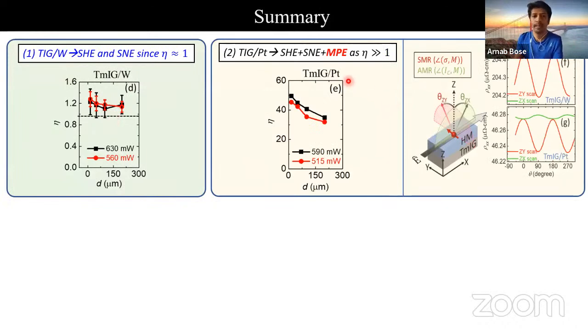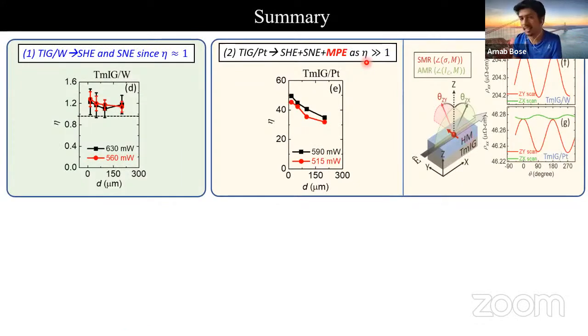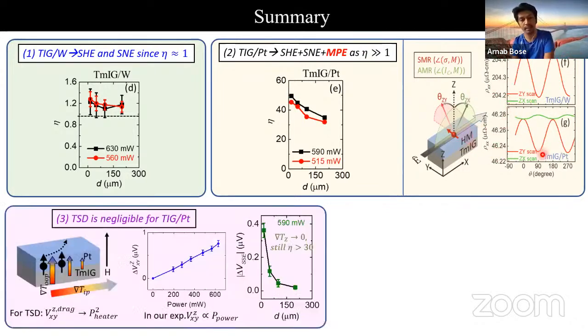We did the same experiment in TMIG platinum. In this case, we find that the value of eta is quite a bit different from 1, and so it suggests that we have an additional contribution, which may originate from the magnetic proximity effect at the interface, which we found in this experiment. We rule out the contribution of thermal spin drag in our experiment from these two data, where we see the linear power dependence and the evidence of a very large value of eta, even when the out-of-plane unintentional thermal gradient